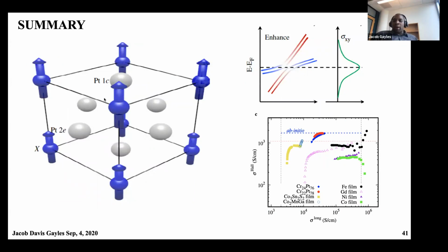I think they're quite well-known materials, so they've been around since the 80s. They're used for magneto-optical recording devices because they have a very large magneto-Kerr effect, which is just the AC equivalent of the anomalous Hall effect. But the actual switching field also depends a lot on the sample growth and the thickness of the film and things like this. So if they've been used for optical recording, then I guess there's enough literature out there so I can have a look. Yeah. Okay.